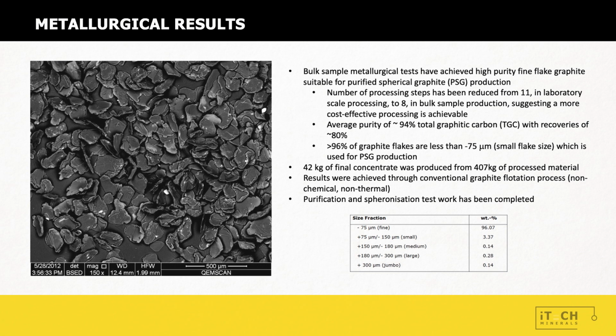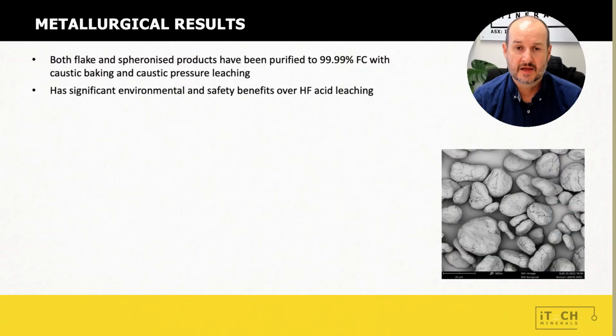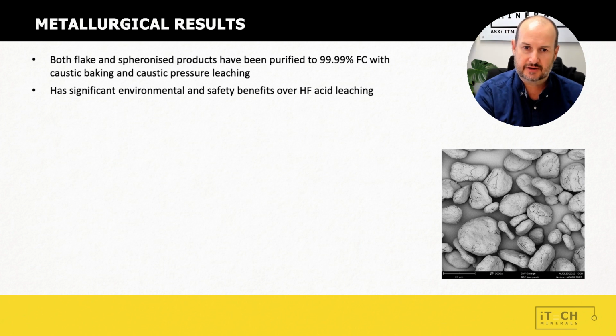So if you have a lot larger flakes or variable flake size, you need to micronize or grind those down, and that uses a lot of energy. Now, having 90% of our material already in the suitable flake size, it will save us a lot on those processing costs. So the next step was then to test the purification of the concentrate and see if we could get it up from 94% total graphitic carbon to well above 99.95%. Now, we were very successful in being able to do that.